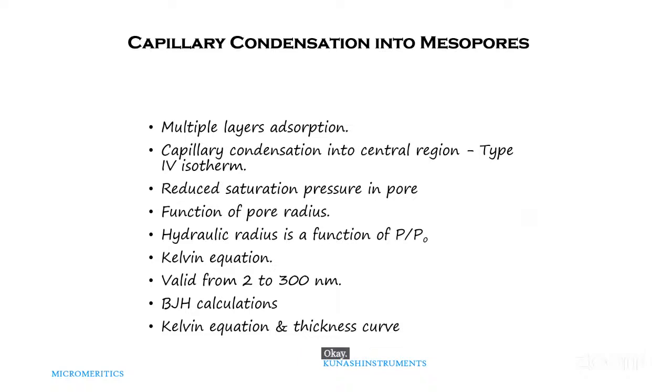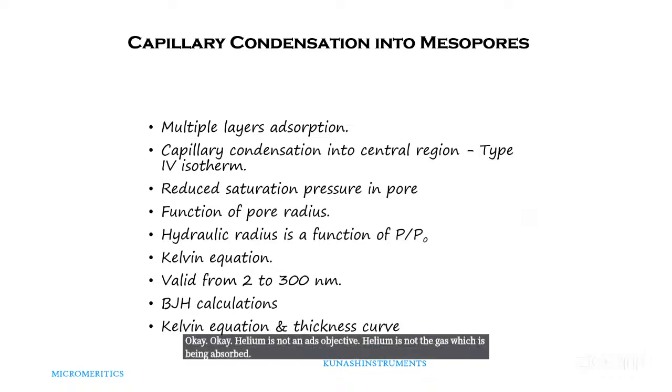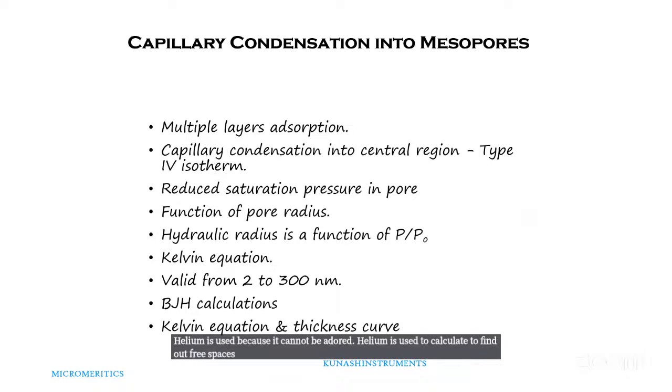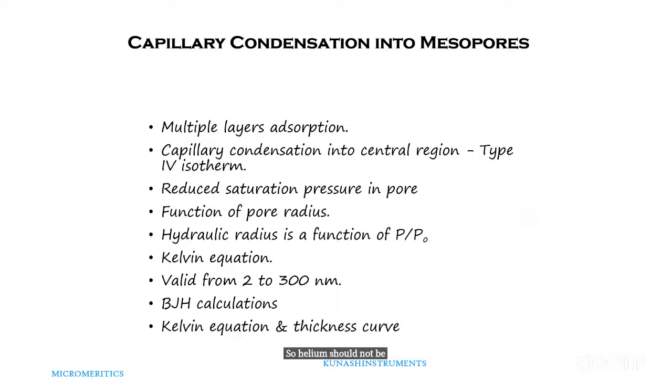Okay. Helium is not an adsorptive. Helium is not the gas which is being adsorbed. Helium is used because it cannot be adsorbed. Helium is used to find out free spaces, and free spaces are defined by the space outside the material. So helium should not be adsorbed. That's why helium is chosen. Helium is not the gas for adsorption.